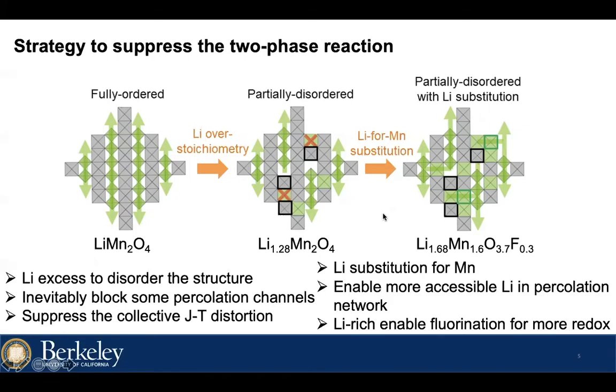The second strategy is to apply lithium for manganese substitution, which enables more accessible lithium. As the disordering in the first strategy blocks some lithium, the second strategy reconnects it into the percolation network. This will also create a lithium-rich environment and make fluorination possible. And fluorination can lower the manganese valence and achieve more manganese redox. As a result, in the designed compound, the cation to anion ratio is over 3 to 4 because of the lithium over-stoichiometry, and the lithium content is more than the manganese content because of the lithium for manganese substitution.